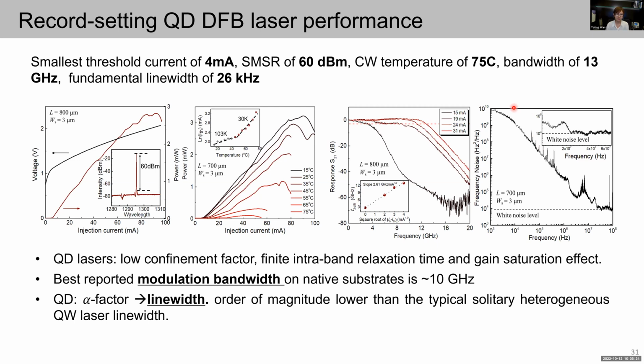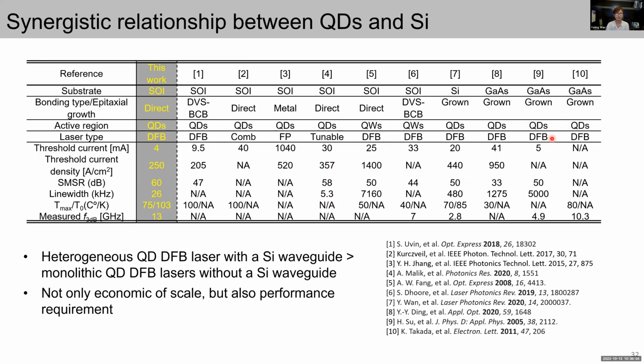And the second point is the linewidth. So still remember that we emphasized many times that one very important aspect of quantum dot lasers is that they have a very small alpha factor. And that small alpha factor can contribute to a significant reduction in the laser linewidth. So here, the Lorentzian linewidth was just 26 kilohertz. This is an order of magnitude lower compared to the typical solitary quantum well hybrid laser linewidth, which is several megahertz. So this table compares the device performance of this work and previously reported work.